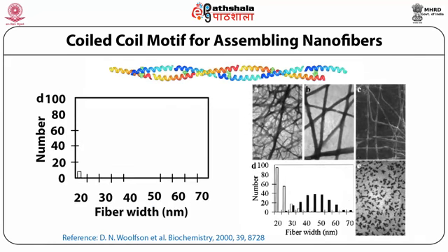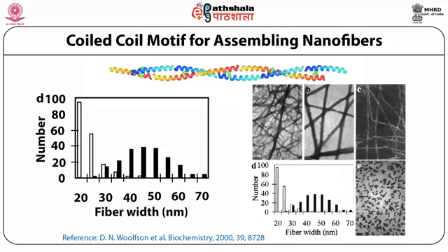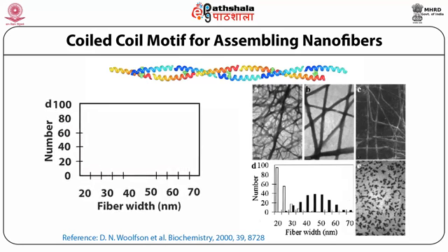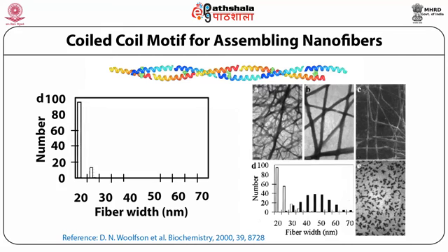However, there was a control experiment where there is no sticky end. If you take another polypeptide chain, that is 3, there is no sticky end possible when 2 and 3 form an assembly. It's like a blunt end, and this has been shown. They form these self-assembled fibers. See, this coiled coil motif is a computer generated model. This coiled coil motif forms very nice nanofibers.